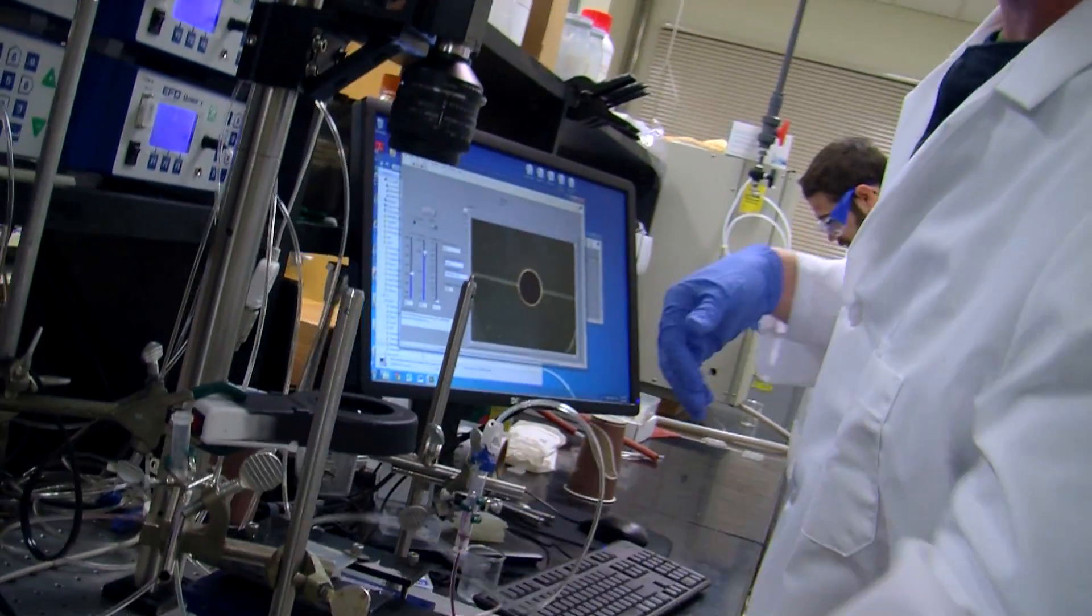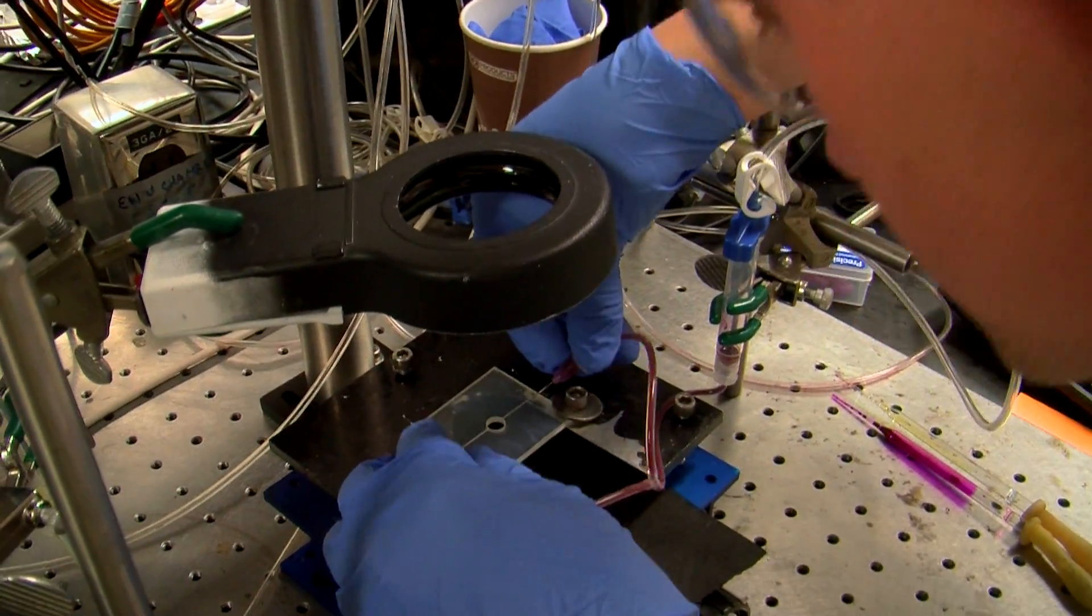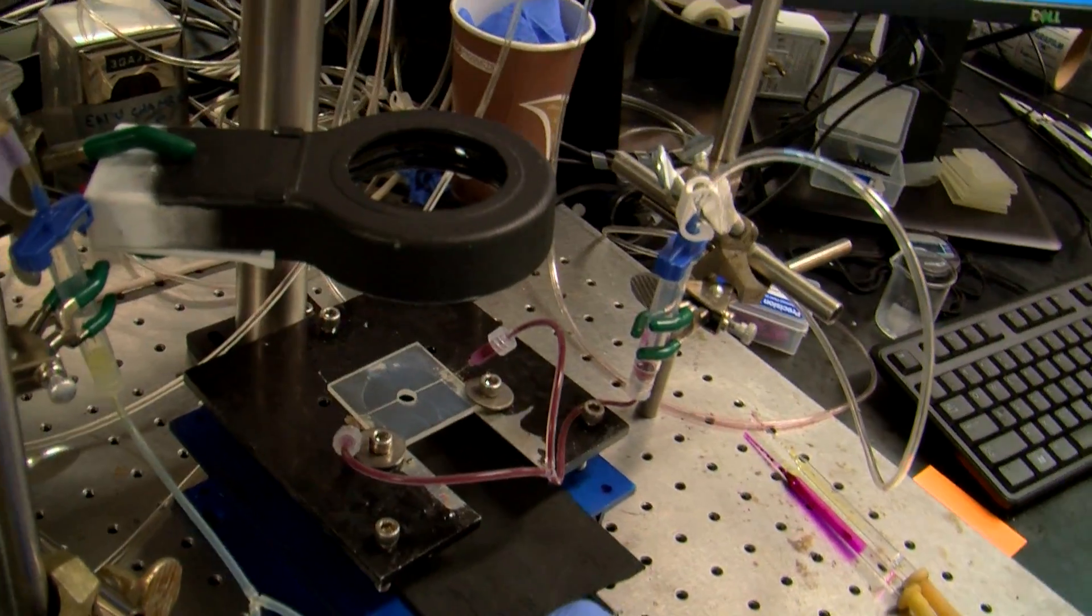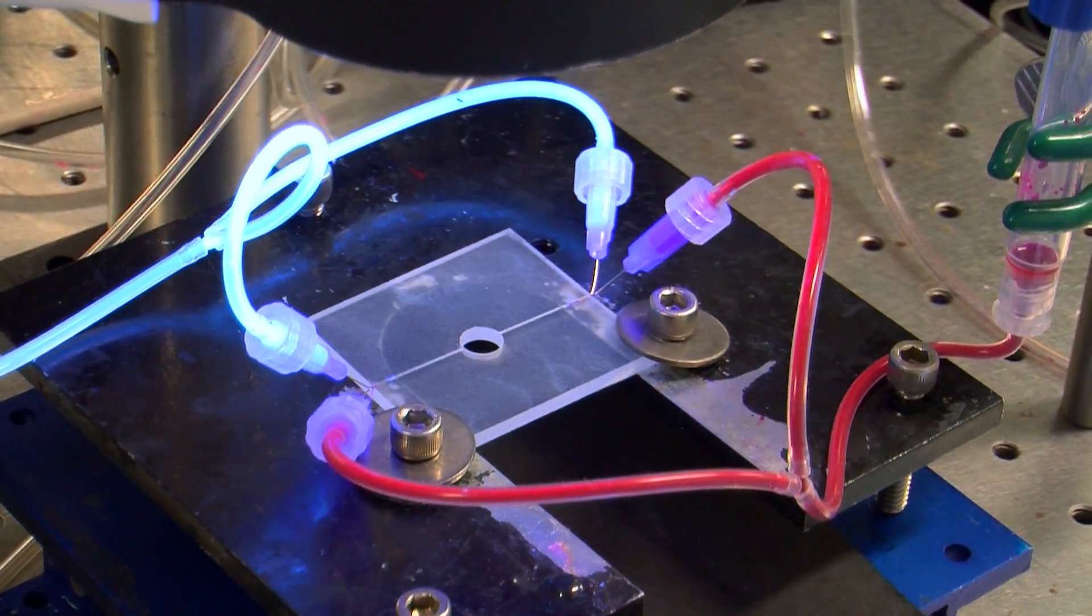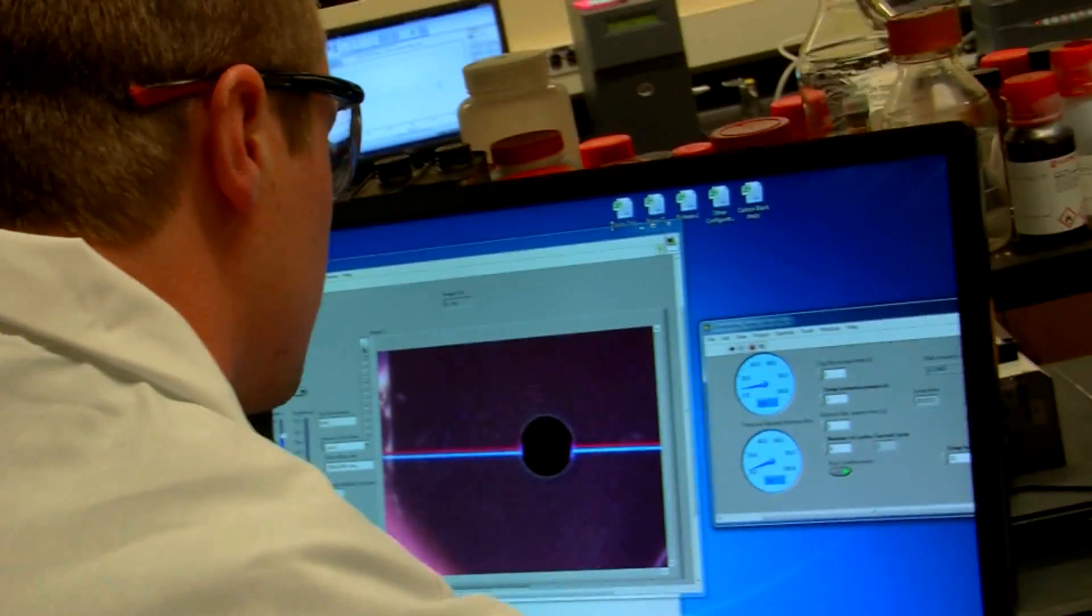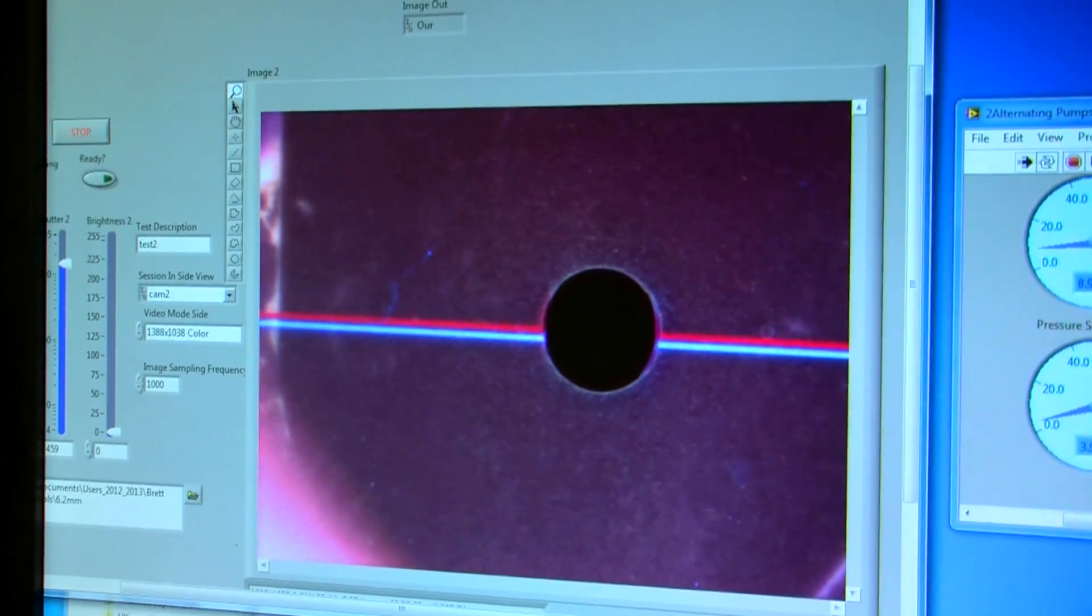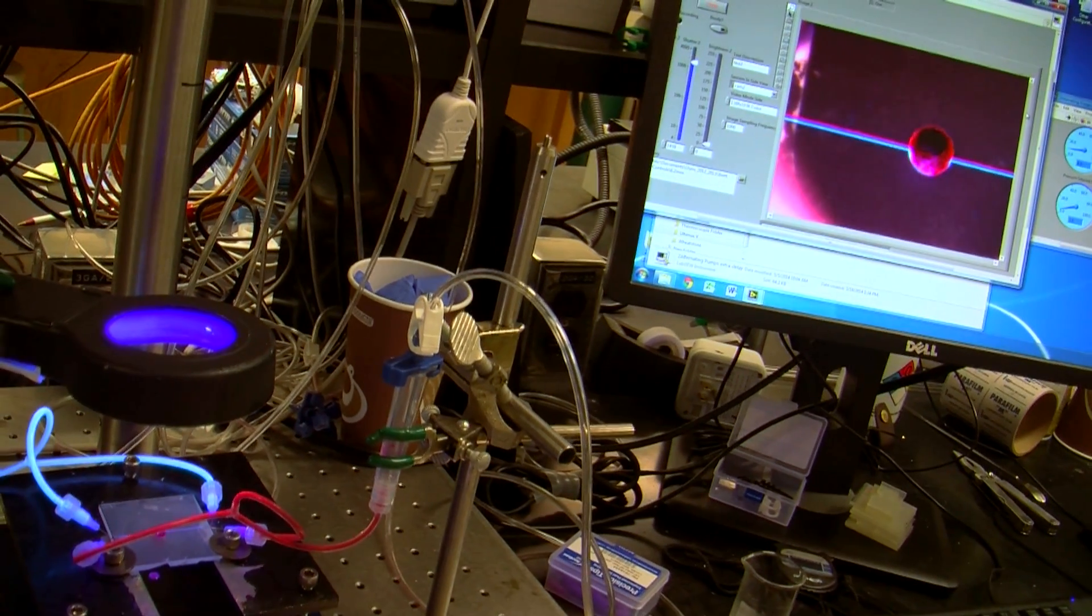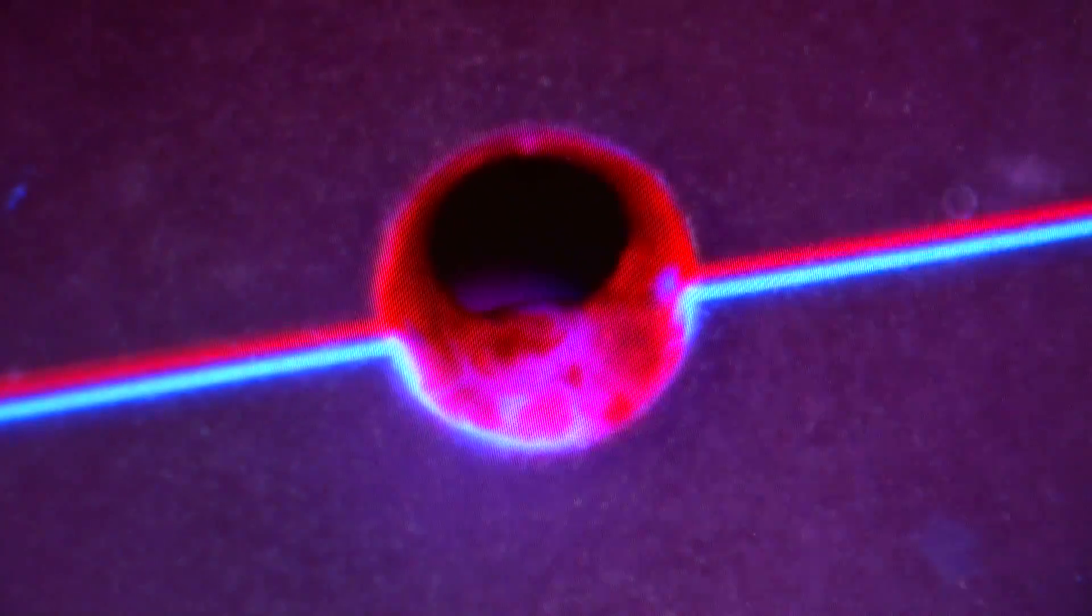What we have done is essentially mimicked the blood clotting feature that you see in humans and other biological systems, so that now the fluids don't just bleed out of the hole anymore. They're actually retained in place and we grow on top of them until we completely seal up the damage itself. The problem here is the gravity, so we had to overcome that. And the way we overcome that is to develop a chemical system that has a gelation that happens very quickly. And that gel-like material helps in retaining it in the hole, if it's a hole, or on a surface, if it's a surface.